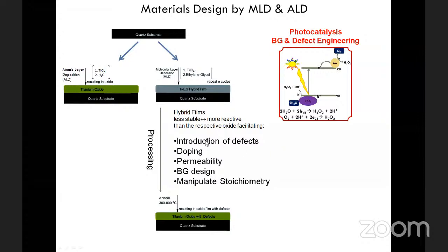For example, introduction of defects. The defects are very important in catalysis and in photocatalysis. So this way we can introduce it controllably. We can introduce doping. We can control the permeability because we start from an inorganic hybrid material, which could be permeable or non-permeable depending on the synthesis conditions, unlike pure oxide that is very difficult to manipulate. Band gap design, and also manipulate the stoichiometry of the final film. So this was the concept.